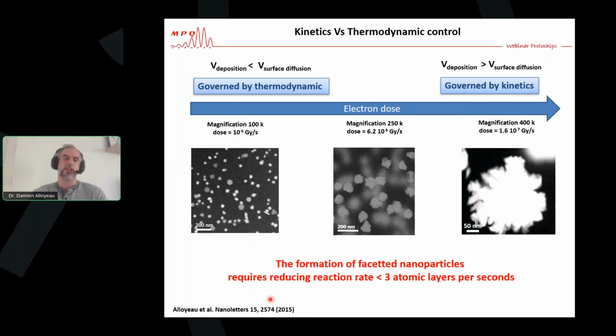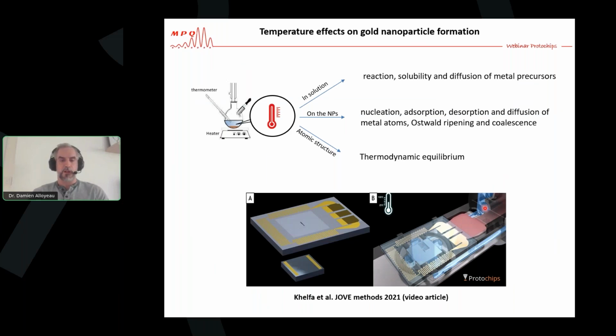Now, more recently, we studied exactly the same type of experiment, but taking into account the temperature. And to do that, we used the sample holder, the liquid cell developed by Protochips, where you have a resistance that is embedded inside the silicon wafer that allows you to control the temperature of the whole liquid cell from 25 to 100 degrees. So we don't have the Triton sample holder that allows you to go to higher temperatures. So this experiment is from 25 to 100 degrees.